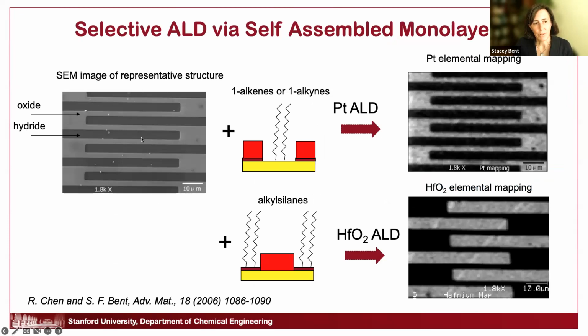So here is a pattern of silicon oxide on silicon, which is terminated by hydrogen. If we do the pathway where we only block the oxide, we can do selective growth of hafnium oxide only on the silicon regions. If we block only the silicon, then we get selective growth, in this case, we were testing it with platinum, only on the oxide regions. So we can get the positive and negative of the pattern there.